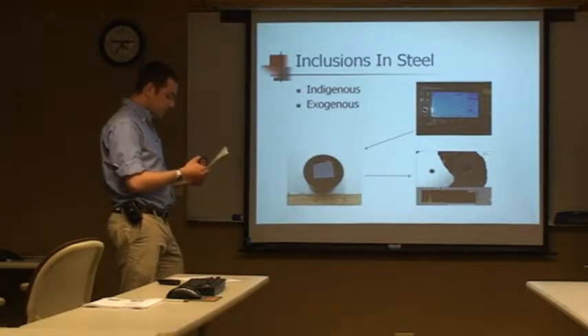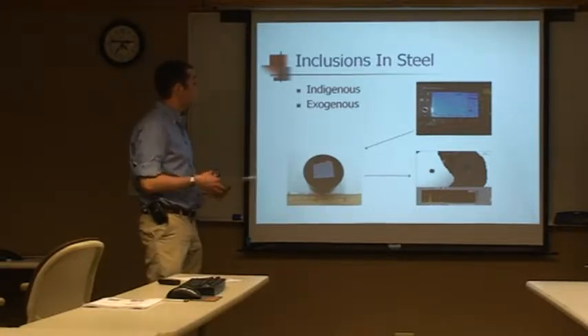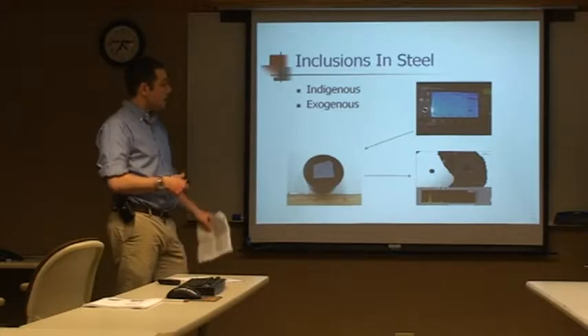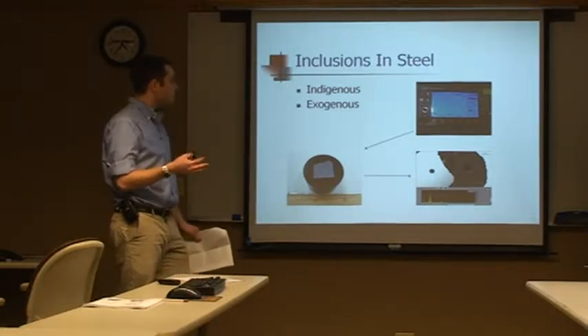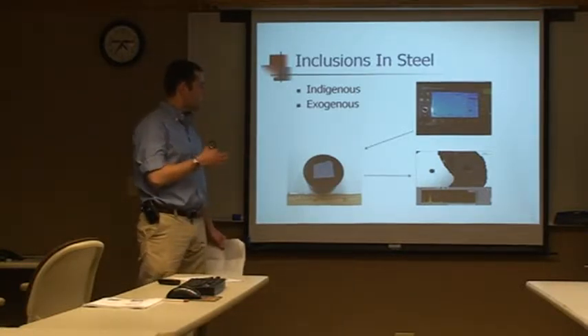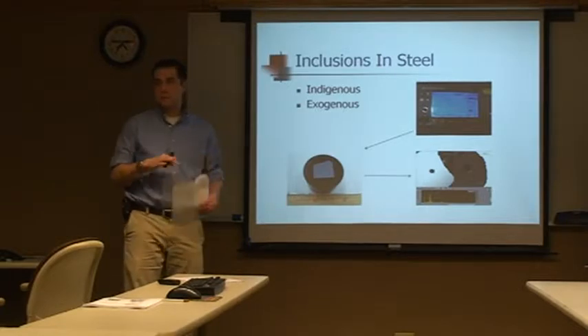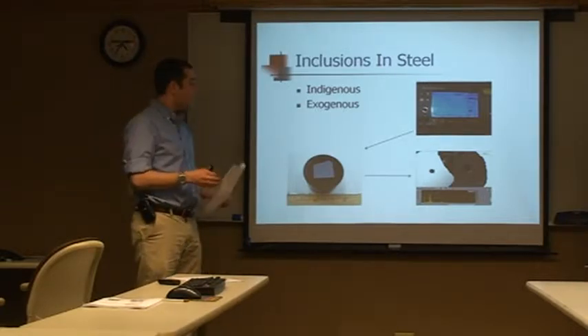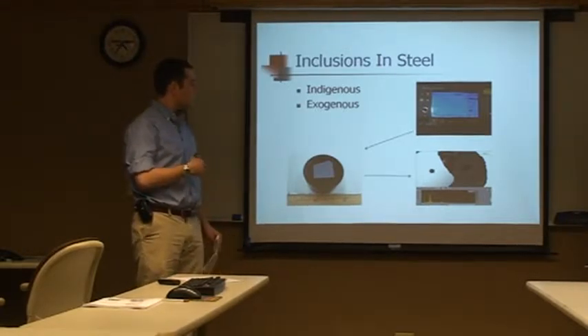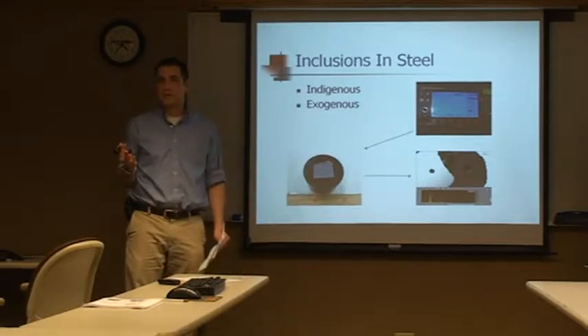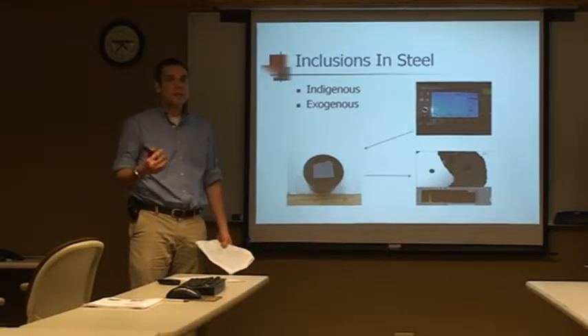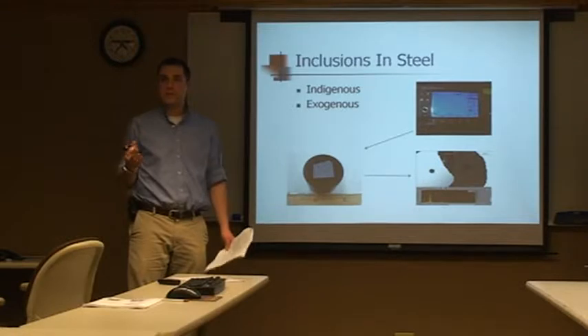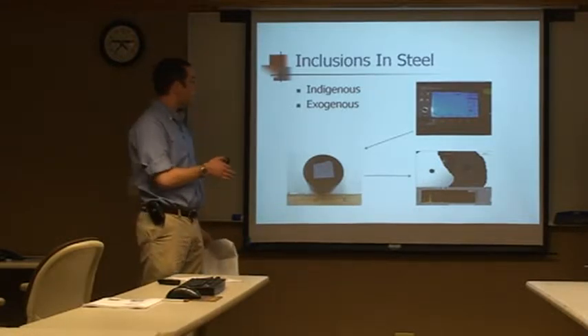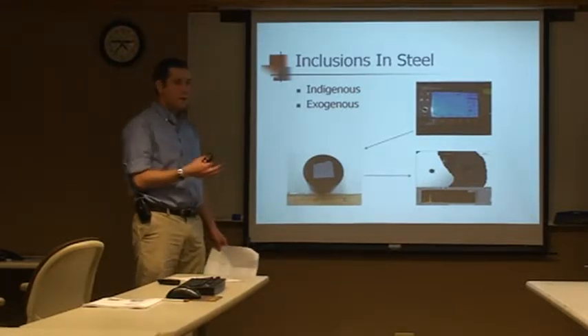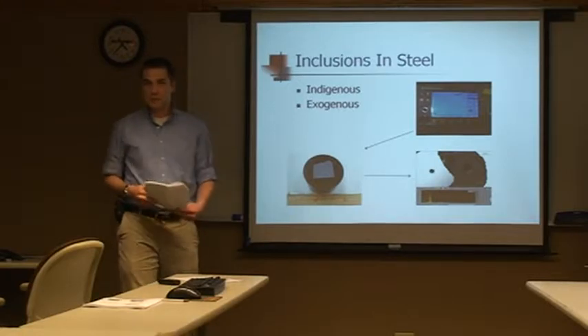Although it's virtually impossible to keep any kind of exogenous material out of the steel, we have lots of controls in place to make sure anything that gets in there is hopefully small. Anything exogenous would typically be picked up by a UT inspection, or ultrasonic testing. After forging is complete, you do a UT test. If there's anything exogenous that could cause problems, it would show up in a test like that.